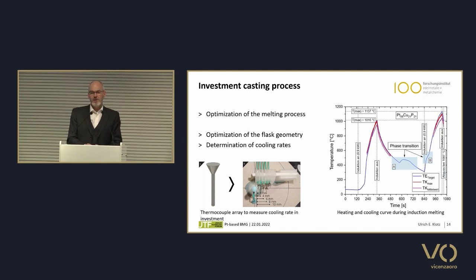So this is how we arranged all the thermocouples with a defined distance from the wax part to determine the cooling rate in our tree. And we also monitored the temperature of the melt with a thermal imaging camera. We see the heating range.